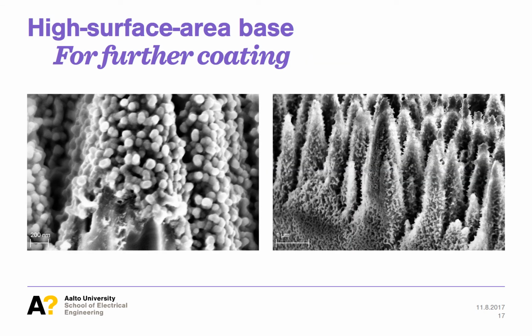Grass-like alumina applications do not end with anti-reflective coatings. It can be advantageous to utilize this extremely high surface area and deposit other functional materials on top. Here you see a nitride and an oxide film deposited by atomic layer deposition on top of grass-like alumina, on top of black silicon for ultimately high surface area. This can be used in sensors, emitters, absorbers, and other devices.